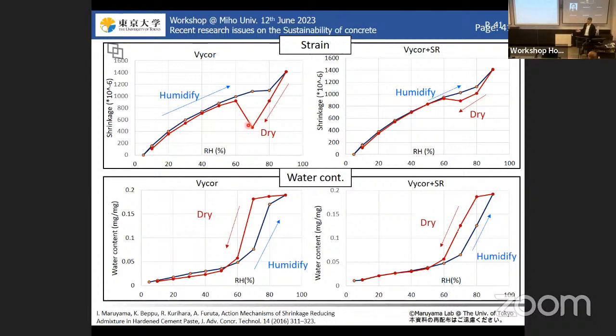And if we add the SRA, due to the change in surface tension and also the equilibrium Kelvin radius, we see the reduction of the hysteresis here. And then based on this, the shrinkage is reduced. As I mentioned, this reduction of the additional shrinkage due to capillary condensation is explained by the change in the equilibrium Kelvin radius and also the surface tension change. So combining these two roles, we see the reduction of the shrinkage from capillary condensation.